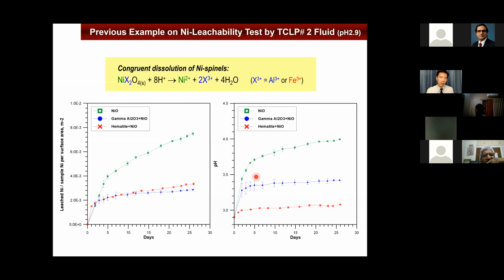However, one thing we should also pay attention to is the leaching behavior, because one of the typical ways we look at the dissolution of a mineral is congruent dissolution, which means, for example, you have one nickel, two trivalent ions, either alumina in our case or iron in our case. Then if it's completely dissolved in a congruent way, then one nickel coming out, you should have two trivalent cations coming out together. We find out that's not necessarily the same for all the minerals, because the response to pH, say in the alumina phase or the iron phases, is different.